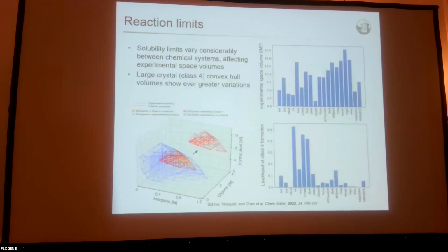A nice thing about the way in which we ingest our data is that we can generate plots in concentration space of the outcome of experiments, and visualize where experiments are working and where they're not working. Some systems like this ethyl ammonium have a lot more points than others, and we can use that to better understand the regions in which we're seeing successful reactions. The experiment convex hull is just the concentration window in which we can work. We can visualize the volume of that, which is dependent upon the solubility of our stock solutions. And then, of course, the convex hull where we actually see success, and it varies quite a lot.